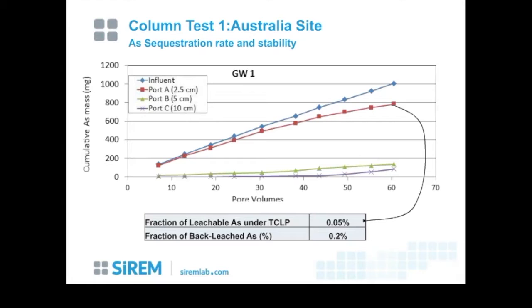And then what we did is we did leaching on the iron from that zone of the column, and we indicated that the iron was strongly sequestered. And then from the back leaching, we only determined that there was 0.2% of the arsenic that was leached. So essentially the take-home message is that arsenic was strongly sequestered and not expected to be released from the spent iron.